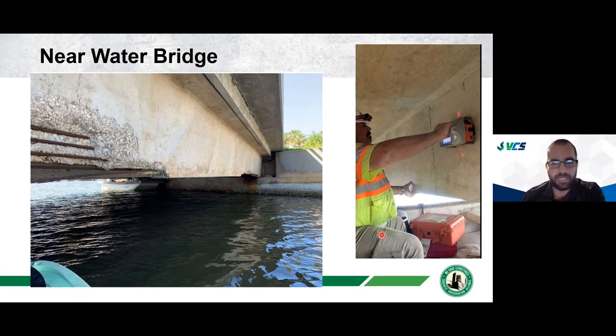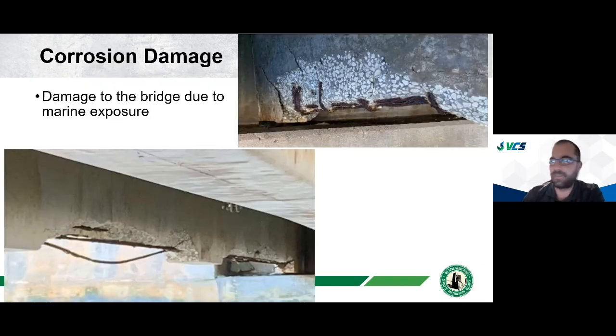And so here you can see a technician with a handheld GPR unit, and he's scanning to identify what the cover depth is of these elements so we can understand where the risk of corrosion is. And that was supposed to be a video, but I don't think that's going to work here, of them scanning it. And so this bridge, obviously, because of its proximity to the water, you can see the type of damage that we're seeing. We're seeing corrosion of the bottom and active deterioration here.